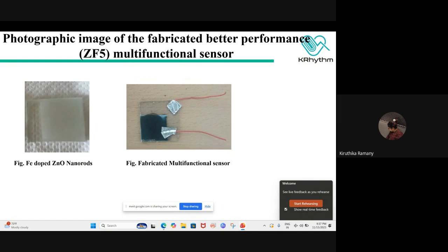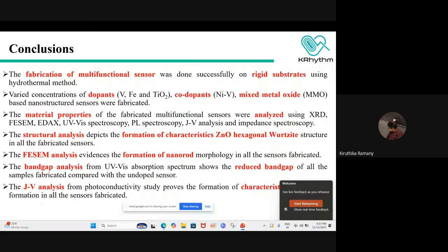So this is the Fe doped zinc oxide nanorods before coating with PEDOT:PSS, and this is the fabricated multifunctional sensor that is coated with PEDOT:PSS. So the conclusion from this research is that fabrication of the multifunctional sensor was done on a rigid substrate. We varied the dopants, co-dopants, and mixed metal oxide based nanostructures, and evaluated their properties.